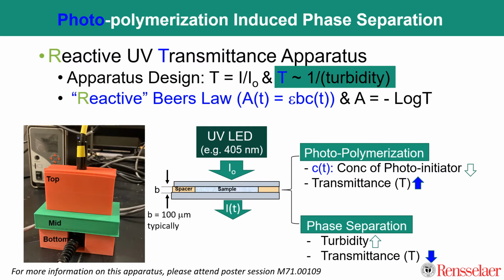So now moving forward, I'm going to introduce our custom-built UV transmittance apparatus, which we use to detect our phase separation occurring in these systems. If you look on the left, you can see that we have these 3D printed pieces that hold everything in place. Our UV LED light source on top, our detector on bottom, and our sample in the middle, which is sandwiched between a glass slide and a cover slip with a spacer in between to allow for a uniform thickness of sample.